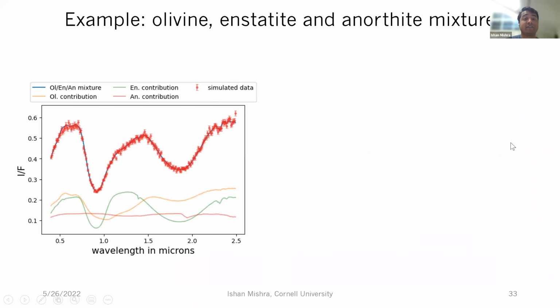To show you an example of this, here I have a reflectance spectrum that's a mixture of three minerals: olivine, enstatite, and anorthite. And in these curves below, I'm showing their individual contribution to the spectrum. So it's basically their reflectance multiplied by their abundance fraction. Anorthite, as you can see, is the weakest contributor, while olivine and enstatite are strong contributors.